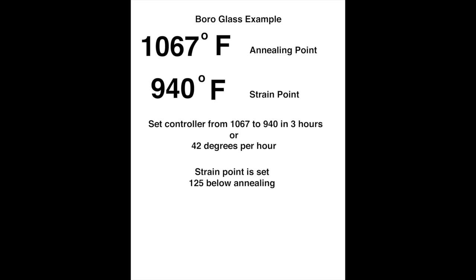Here's a chart for borosilicate glass. The annealing point is 1067 and the strain point is 940. Again, we have 125 degrees below the annealing point to the strain point. And depending on your controller, once again, you can just put your 2 set points in and plug in the hours, 1, 2, 3 hours, whatever works out for your glass. And in this case, for 3 hours, you'd use 42 degrees per hour, and that would give you 3 hours.